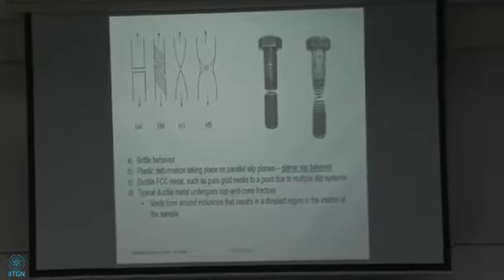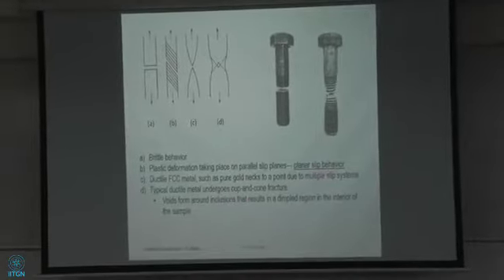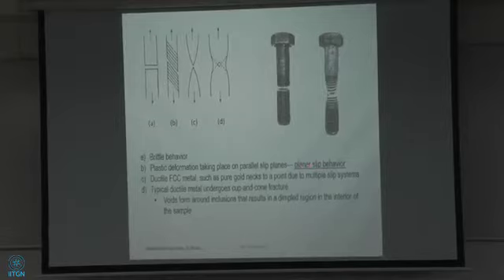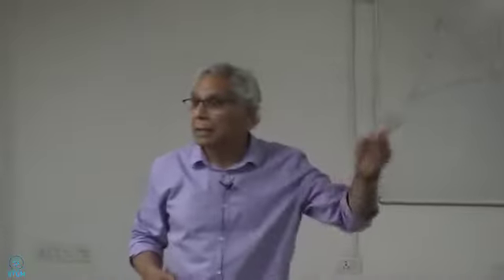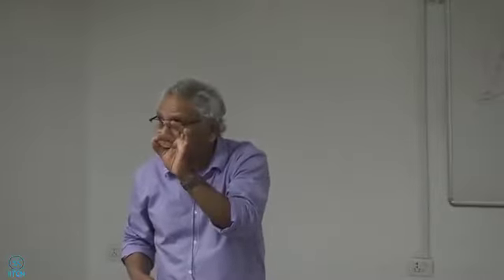Okay, so here I wanted to, I know why I highlighted this. I was wondering why did I highlight this? So when you have slip in this single slip system, that is called planar slip material, planar slip behavior. You will encounter this term a lot in the literature if you're doing your PhD in this area of nickel-based superalloys. Anytime a dislocation is cutting a precipitate, for instance, shearing a precipitate, and if it's going along that one plane, it's a planar slip material.